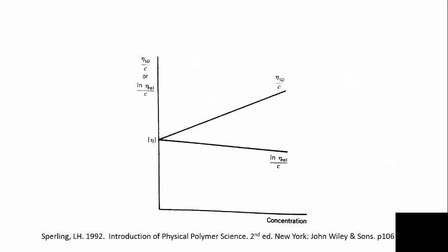So just to remind you, we're going to find the intrinsic viscosity by doing this plot here. We'll do both: the specific viscosity curve, but then also the relative viscosity curve should end up at the same point on the y-axis, concentration 0. And you'll do this measurement or series of measurements, calculate or extrapolate to find the intrinsic viscosity for both the normal and the degraded or cleaved polyvinyl alcohol.